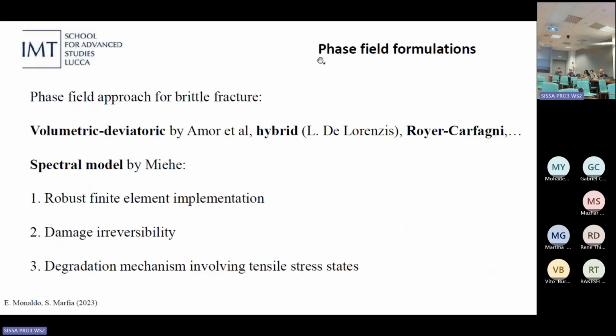Okay, so talking about the phase field formulation for brittle fracture, there is basically a jungle of phase field formulations for brittle fracture. We have many models, for instance, the volumetric deviatoric approach by Amor, the hybrid approach by Laura De Lorenzis, the Royer-Carfagni model. Actually, for the present work, we adopted the spectral model by Miehe, which is known to be very robust in terms of finite element implementation. It accounts for damage reversibility and also takes into account the degradation mechanisms, which involve internal stress states of tensile